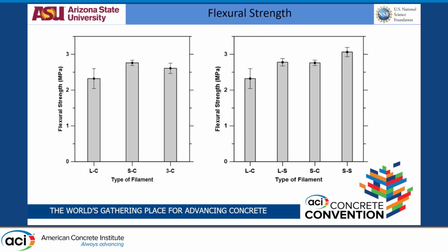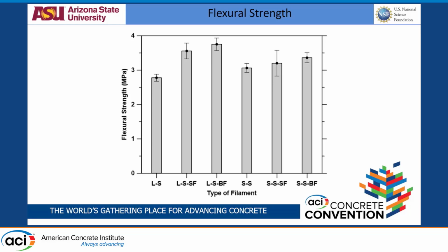With the S-shape and staggering combined, we got an even further increase in the flexural strength. So it's quite significant to see that the same mix could provide us better strength if we just changed our way of printing those elements.